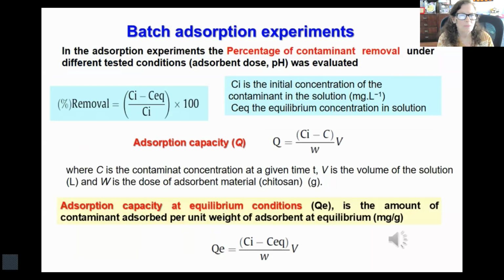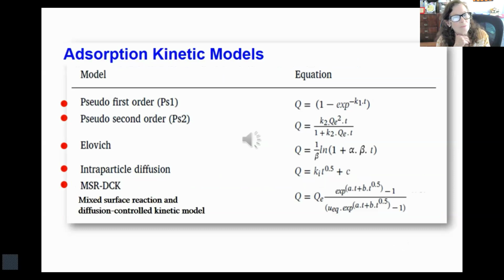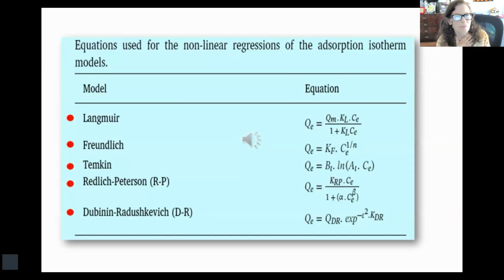In the batch adsorption experiments, the percentage of contaminant removal under different tested conditions was evaluated. We also measured the adsorption capacity at equilibrium conditions, that is the amount of contaminant adsorbed per unit weight of adsorbent at equilibrium. These are the adsorption kinetic models that we tested with the respective equations: pseudo first order, pseudo second order, Elovich, intraparticle diffusion, and mixed surface reaction and diffusion control kinetic model. The tested adsorption isotherm equations were Langmuir, Freundlich, Temkin, Redlich-Peterson, and Dubinin-Radushkevich.